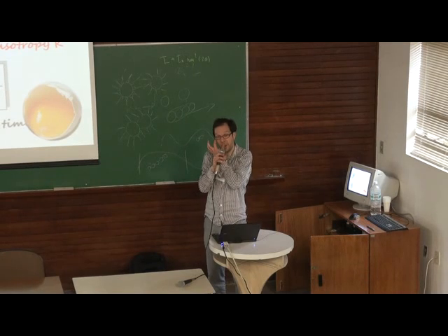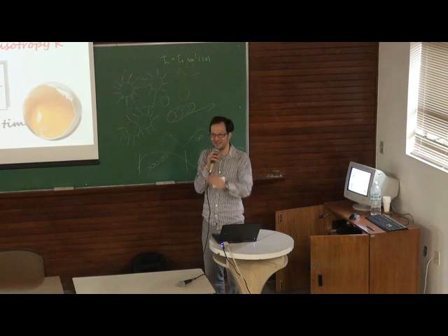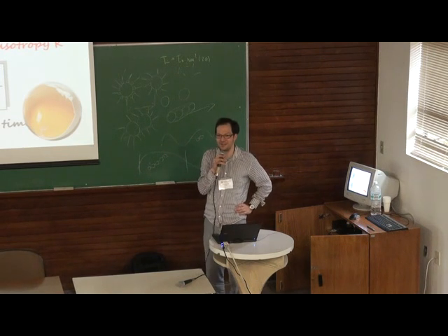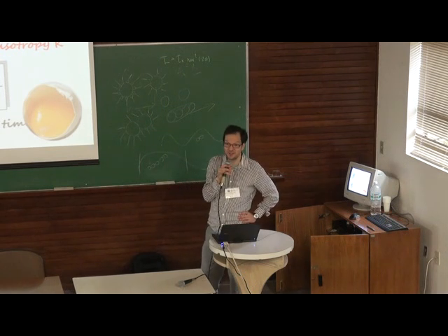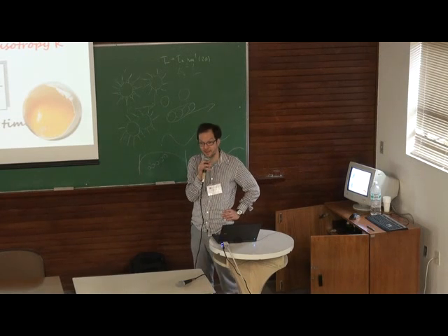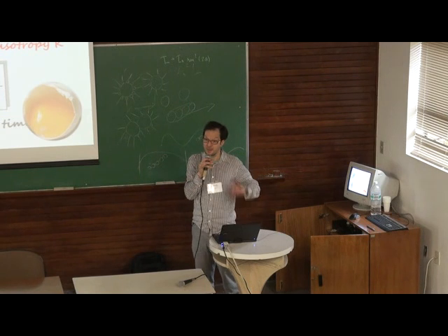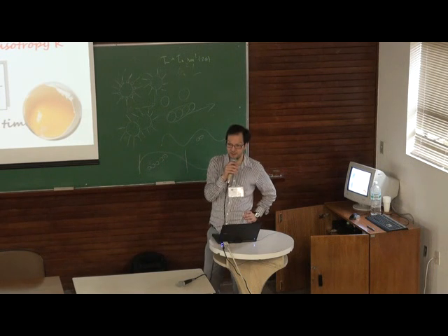More questions? Here you have experts in X-ray diffraction, and I was thinking maybe we can try to investigate this using small angle X-ray. Yes, this is a common technique to use. If you investigate this before applying your field, you can more or less quantify these big particles, and then later when you put your field on, by this difference you can figure out what has changed.